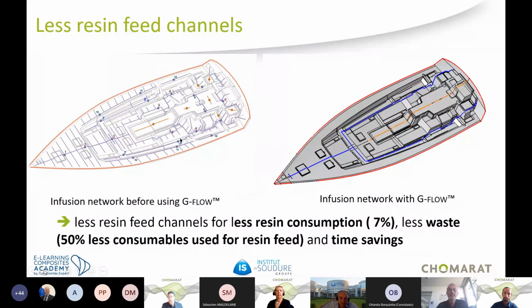The challenge was to apply the G-Flow in a boat deck, with the objective of reducing the environmental impact, the consumption, and overall the cost. On the left, we have in blue the infusion network before using a G-Flow. On the right side, the infusion network with G-Flow, which is much more simple. The result is a global positive impact. 50% less accessory use for the network with the G-Flow means a positive ecological impact, and then 7% reduction in resin consumption, so time and cost saving.